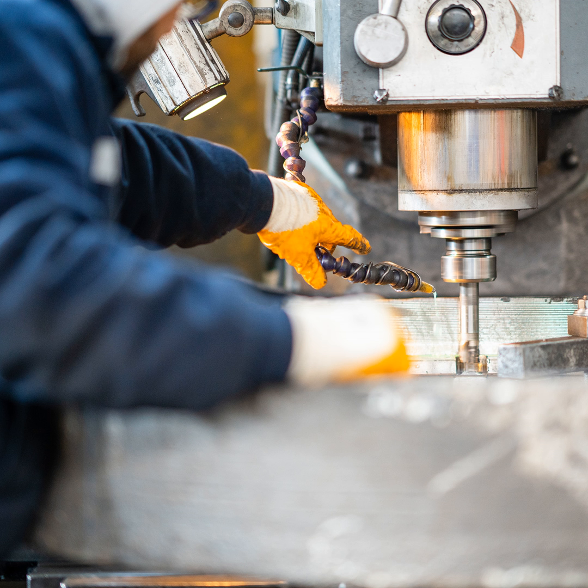Here's a scenario in terms of what HEM can provide you versus a traditional mill. This has actually been done and tested, so it's really not a potential, it is actual. We used our 1/2-inch 6 flute OptiMill, OptiLine mill into titanium 6AL4V. We did a comparison of light roughing, where we engaged the radial step over, what we typically would do, 20%, .100 radial step over, and we have to be limited in terms of our axial depth, which was 5/8. We fed that at a little over 2.5 thou, which gave us an actual chip thickness right around 2 thou. You could add to that if you wanted to. You'd get a little bit of a bump up for radial chip thinning.